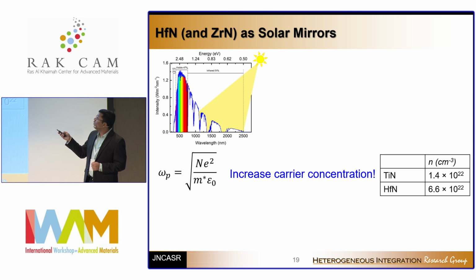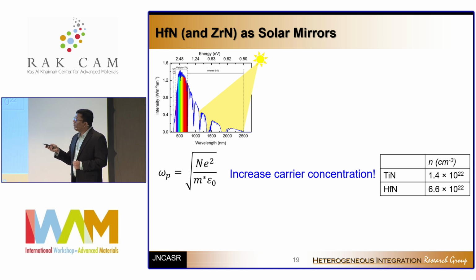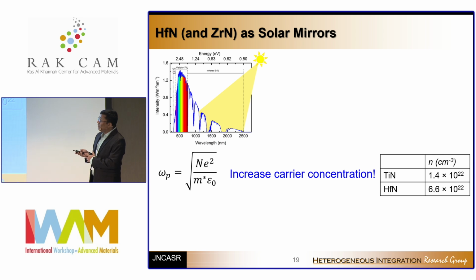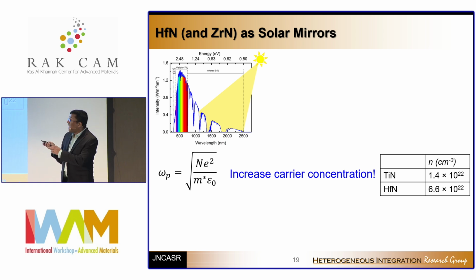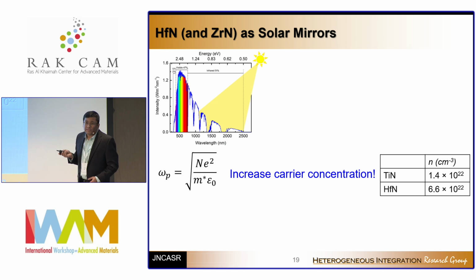Now, in the case of a solar mirror, you really want to reflect the entire solar spectrum. So if we try to use titanium nitride, there is a problem. The problem is the solar spectrum shows a peak at around 500 nanometers, and titanium nitride's ENZ frequency is also 500 nanometers. So that practically means that a huge portion of the light in the UV or visible range we cannot reflect with titanium nitride.